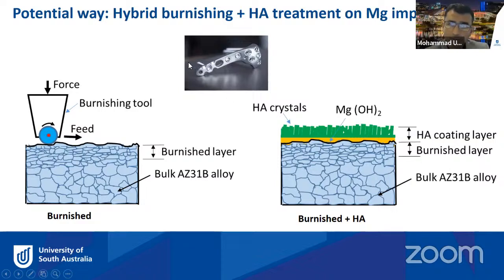In this particular approach, we have applied that to control the degradation of the magnesium implant. After the ball burnishing, we also apply the hydroxyapatite coating. We call it the hybrid surface engineering technique: hybrid ball burnishing plus HA treatment. By applying the hydroxyapatite coating, we create a barrier layer onto the burnished surface. By adding this layer or coating, we further augment the corrosion resistance of the magnesium alloy. So by doing that, we can extend the degradation or delay the degradation process for some time.